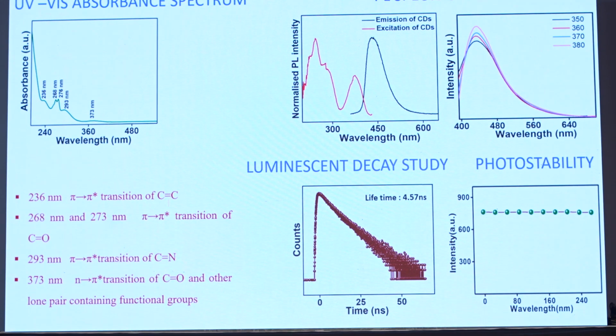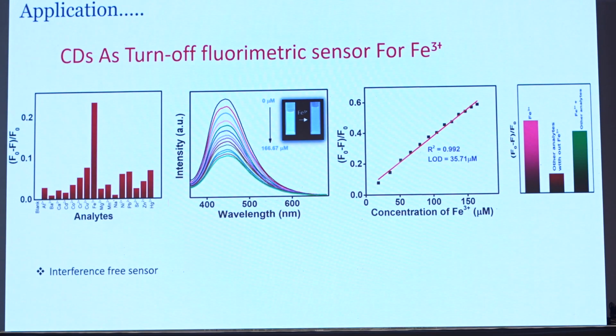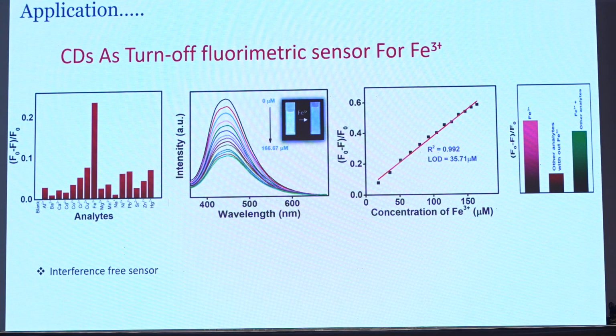Further study shows that our carbon dot shows wavelength independent emission. And the luminescent decay study shows that the lifetime of the synthesized carbon dot is 4.57 nanosecond, and the synthesized carbon dot shows excellent photostability. Moving on to the application. We have used the synthesized carbon dot as a turn-off fluorometric sensor.